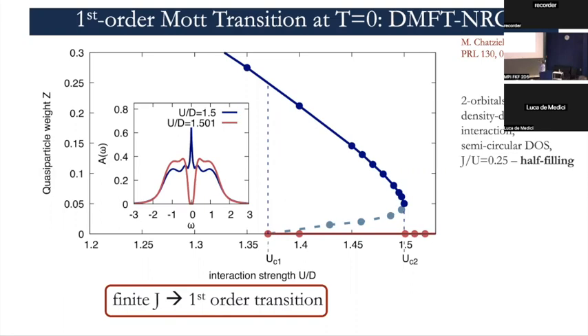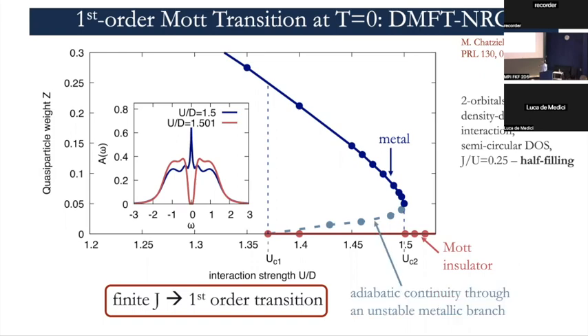So what is interesting is how this jump happens. Here we see the lower part of the previous curve, in which Z is vanishing in this metallic branch. But before jumping to this red branch, which is Mott insulating, you see that there is actually an unstable branch connecting the two stable branches, which is still metallic, and so Z goes back in U. So you can say that there is a folding of this structure of solutions, which of course means that if you scan the parameter space, you will jump from this solution to the other, or if you go back, you will have what we call a coexistence zone of solutions. But really, the structure of solutions is adiabatically connected through this unstable metallic branch.